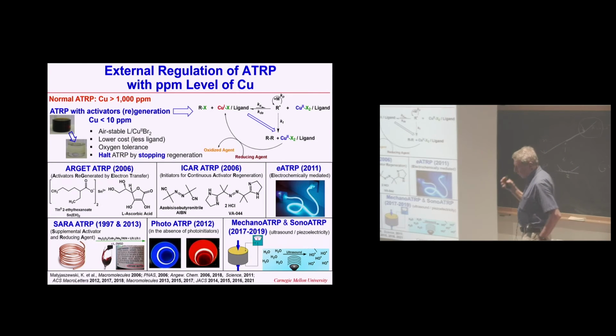So we are working with systems which can decrease the concentration of copper from 1,000 ppm to 10 ppm. You could look at this reaction mixture. If you go to 1 ppm, for many applications, you don't need to remove copper. For some, you still need to remove it, for example, for biological systems by dialysis. But if you use such a low concentration of copper, I mentioned to you that every act of termination will convert these activators to deactivators irreversibly, and the reaction would stop. So I need to regenerate it using various reducing agents.